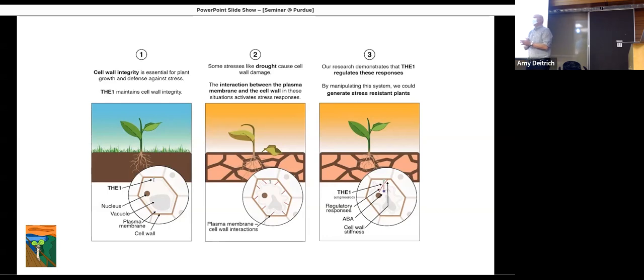When we measure cell wall composition and structure in ABA mutants, which are deficient in ABA, we actually find a reduced cellulose level. So it seems that in the ABA mutants, the cell wall has adapted to a change in ABA level. What I currently assume is that with procuste we have a similar situation, just the other way around. Essentially the seedling has adapted to the reduced cellulose production, and therefore procuste has only a limited effect. But this is guessing.